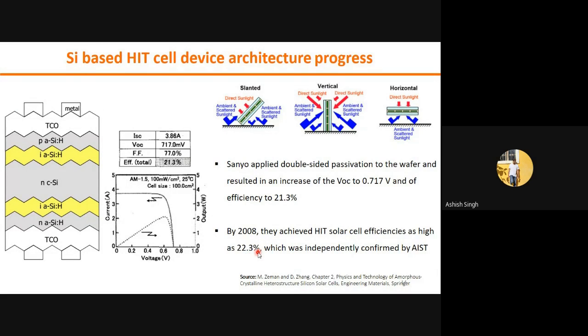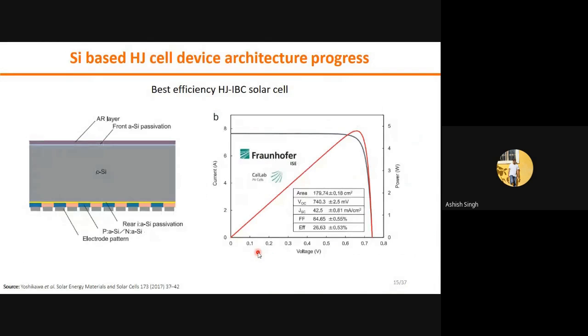In between that time, Kaneka started working on it, and they reported the best efficiency of heterojunction solar cell, and they could make 26.7% efficiency, and they called this device the heterojunction back contact solar cell. If you notice, they use crystalline silicon and then passivation and the anti-reflection coating on the top side, no metal contact on the top side. Both electron and hole collection is coming from the bottom side only. So 100% area is open for the solar radiation.